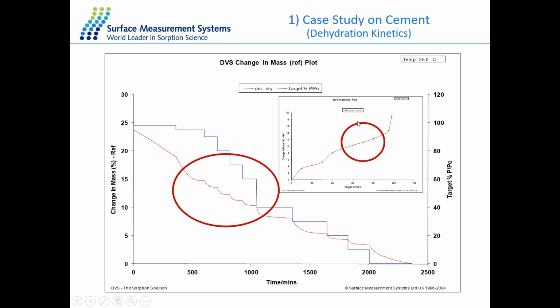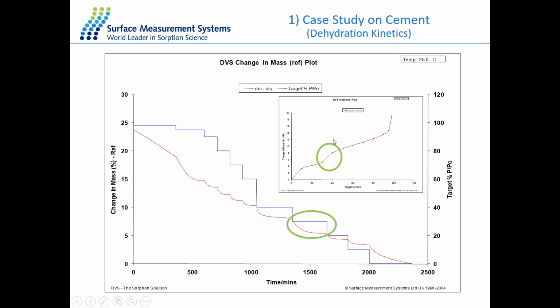And there is a gradual mass loss between 90% RH and 40% RH. And then it is followed by another sharper mass loss at 30% RH, which may be due to the loss of internal or hydrated water. And there is another sharp loss in the mass as the sample is fully dried at 0% RH. So here the DVS method is a very quick and easy way to detect these changes happening during the dehydration process.